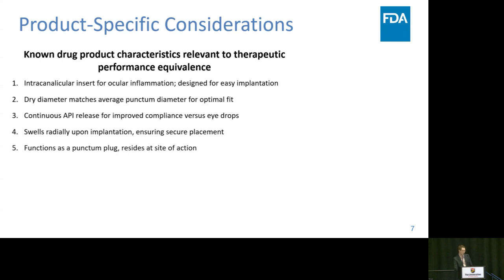And it functions as a punctum plug. It resides there at the site of action. The tear fluid swells it and gradually courses through the hydrogel and absorbs the dexamethasone that's entrapped within it, and it bathes the ocular tissues with a very low concentration dexamethasone fluid. And then oftentimes, in this case, it contains a dye that's used as a visual aid. This helps the practitioner to verify that it's retained at the site of interest.